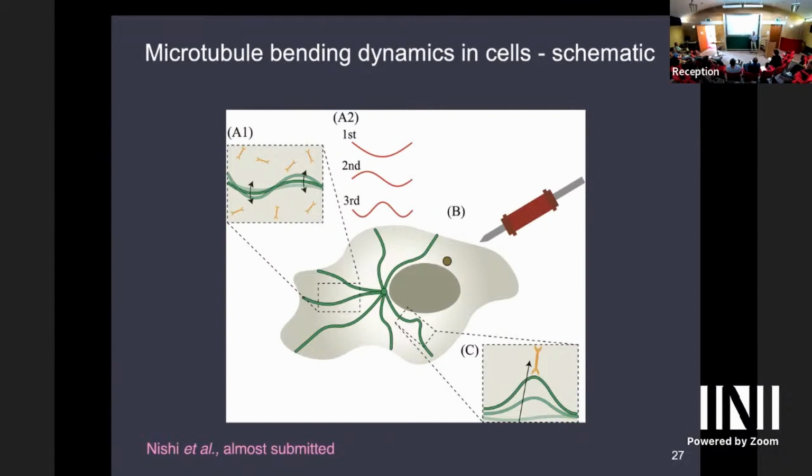So we don't introduce anything, neither beads nor filaments, no artificial probes into the cell, and just use the existing filaments in there and try to basically hijack those filaments and their fluctuations to learn something about both the filaments and the viscoelastic embedding and the forces. So we basically have three unknowns in this problem. We are partially unknowns: the bending elasticity of the filaments, the local embedding in the cytoskeleton, and of course the driving forces. And the basic message in the end is going to be, if you know one of those, you can basically measure the other two.